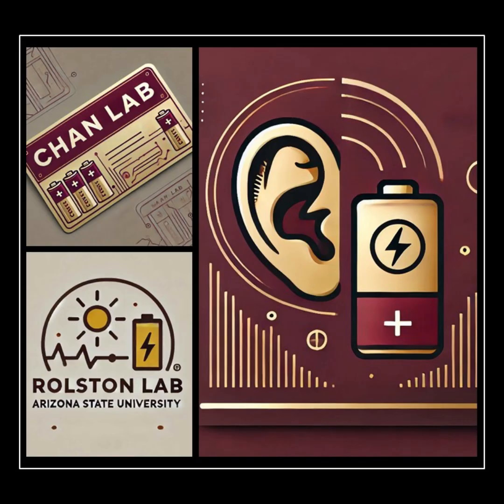And this is where it connects to something we've discussed before, something potentially dangerous. Dendrites, those little metal spikes. How does lithium carbonate lead to those? Right, this is the really critical safety part. Under certain conditions, especially if you're charging fast, that lithium carbonate layer can actually be chemically reduced. Reduced, meaning it changes chemically. Yeah, it can form lithium compounds that conduct electricity. And these compounds tend to collect in the grain boundaries of the LLZTO, like tiny cracks or seams between the crystals. And these conductive spots become nucleation sites, little starting points for lithium metal dendrites to begin growing.